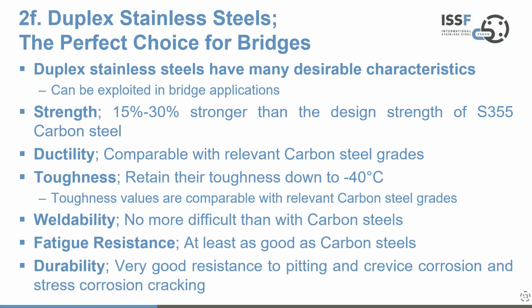These products are no more difficult than carbon steels to weld. Their fatigue resistance is at least as good as that of carbon steels, and in many cases better. And where this family of grades really wins is in terms of its resistance to corrosion, particularly pitting, crevice, as I mentioned a moment ago, stress corrosion cracking. So those are the real characteristics of duplex stainless steels that make them really interesting.